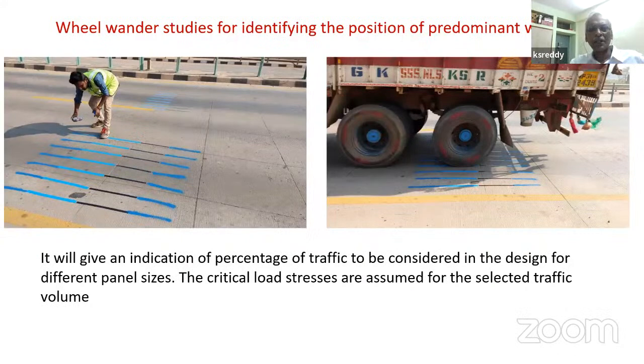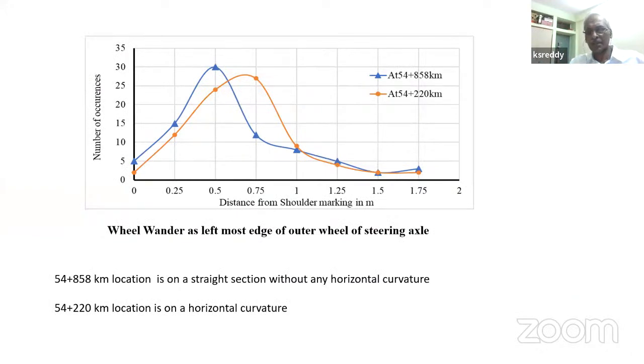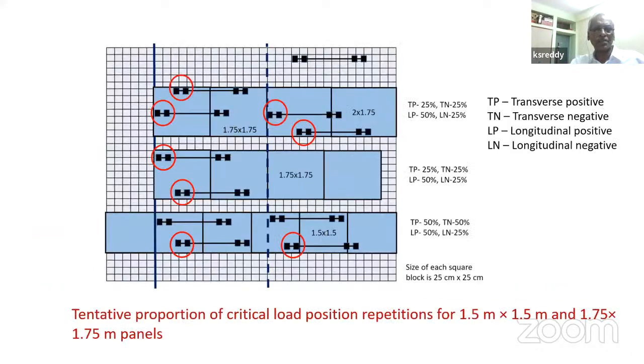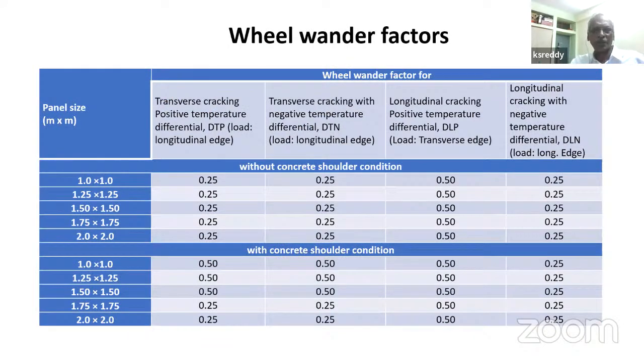We also carried out lateral distribution, lateral wander, of wheel loads to identify, for different critical combinations, what could be the percentage of vehicles that we should consider. These are the results that we obtained from that. And this is the summary of recommendations for different load positions and different panel sizes: what could be the percentage of loads that we can consider for different critical failure cases, transverse cracking, longitudinal cracking, top-down, bottom-up.